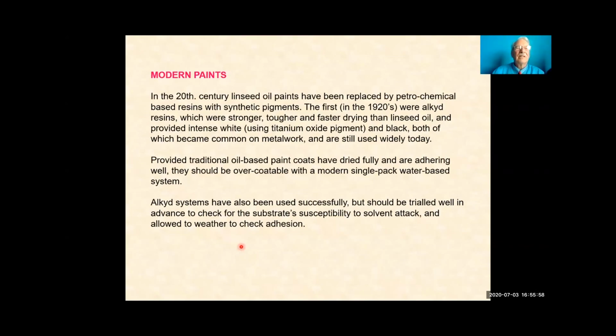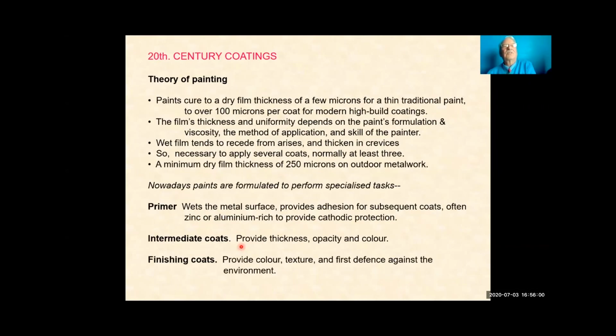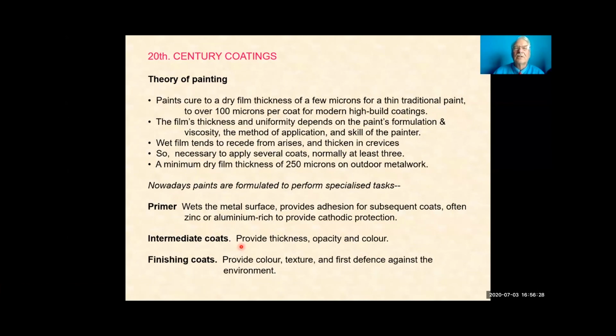The theory of painting. Paints cure to a dry film thickness of a few microns for a traditional paint to over 100 microns per coat for modern high build coatings. A micron is a thousandth of a millimeter, and on ferrous metals, that's the usual way of specifying paint. Modern paint specifications tend not to give the number of coats now, but the final thickness of paint. And it's easy to measure. I'll show you how later.